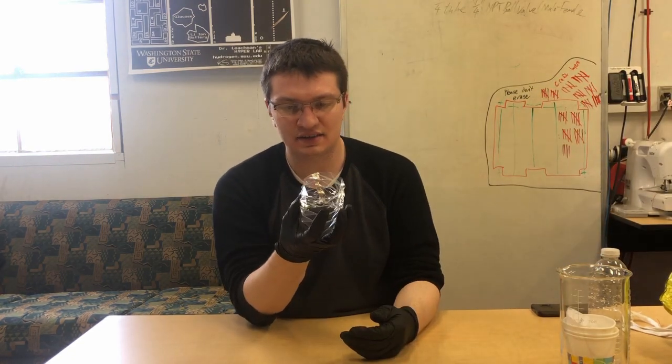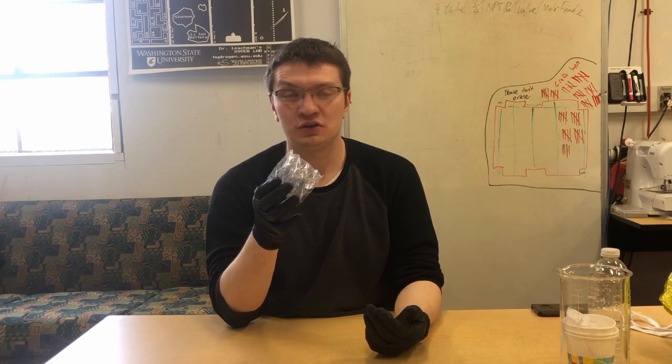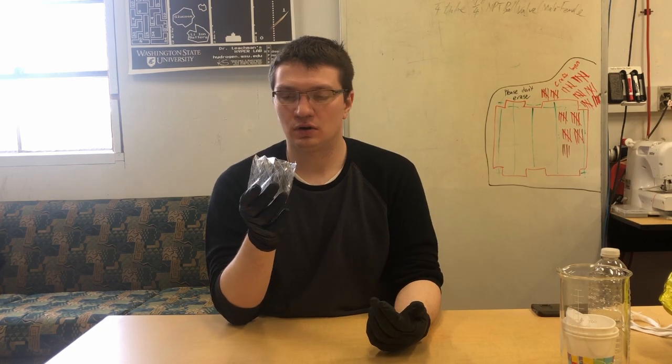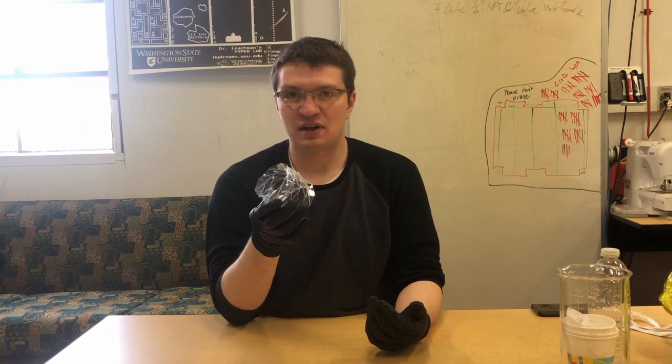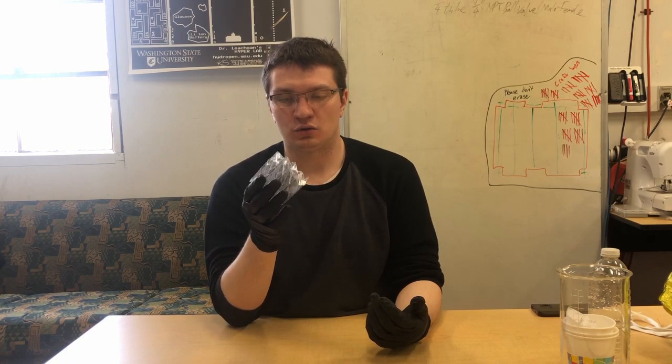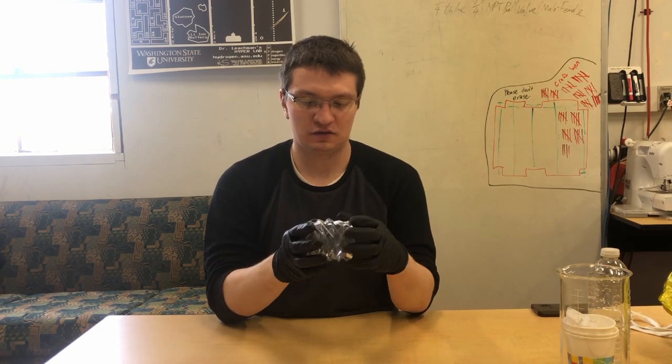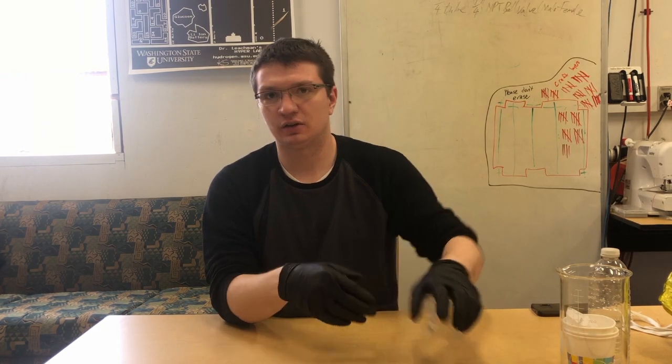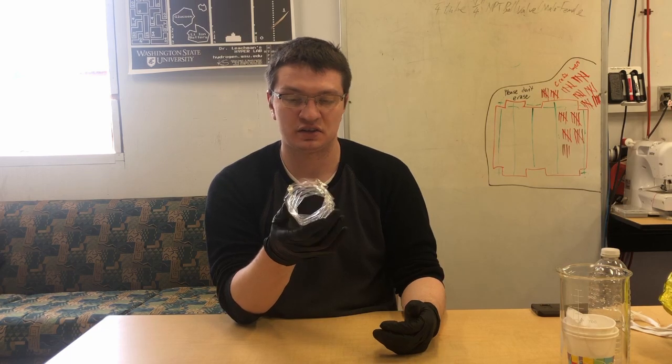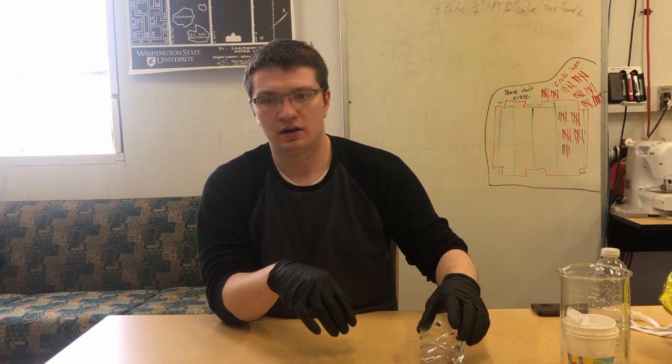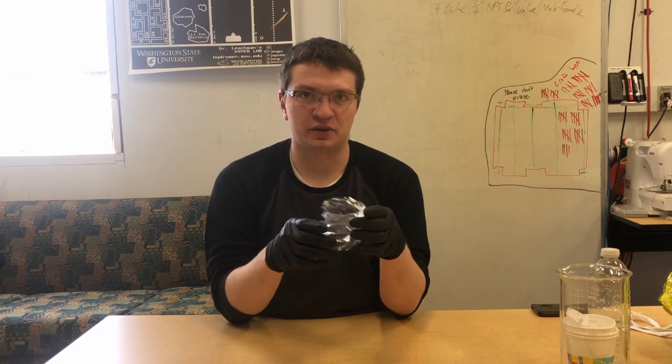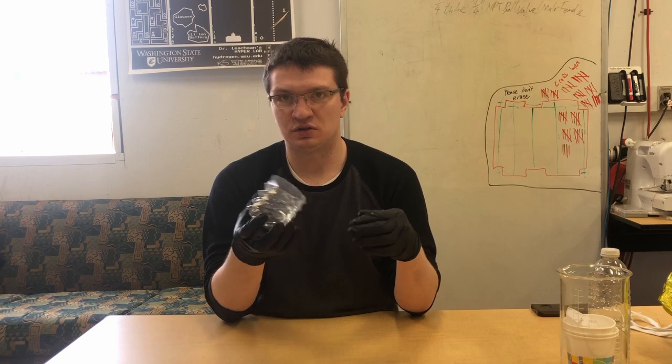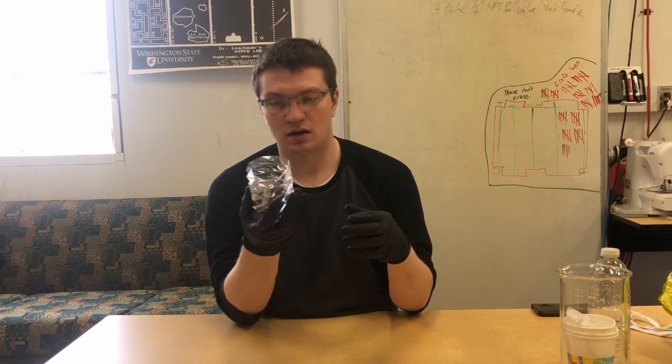I've actually tested this where you can just watch YouTube videos at home, get some thin plastic films, about three one-thousandths of an inch will do, and just fold it into the shape. And then if you had some LN2 on hand, you'd be able to simply cycle it hundreds of times and still not run into any issues of it tearing. The first bellows I ever fabricated and the first time I've actually ever done origami, I was able to watch a YouTube video and make a bellows in a couple hours.